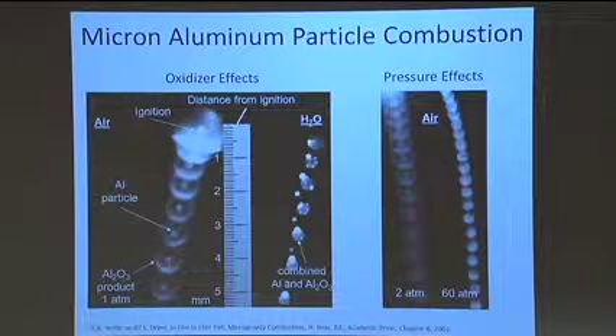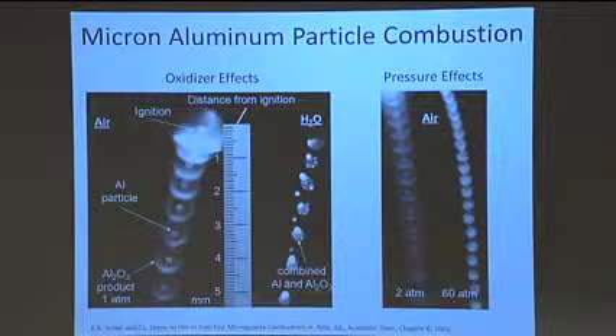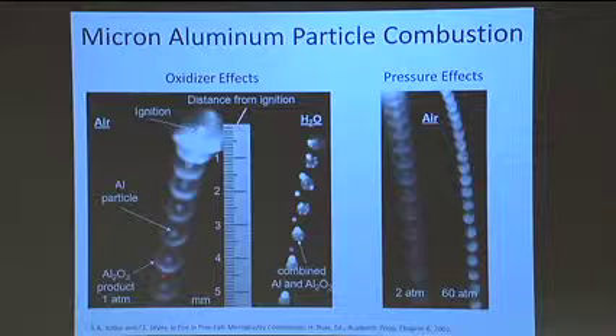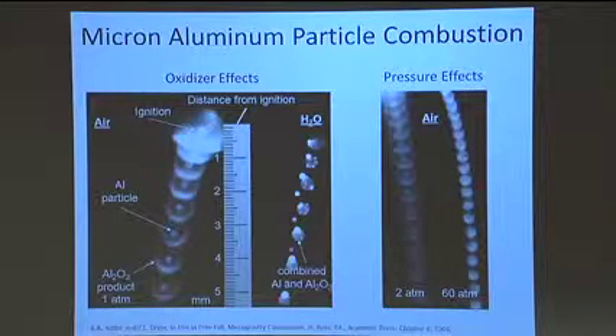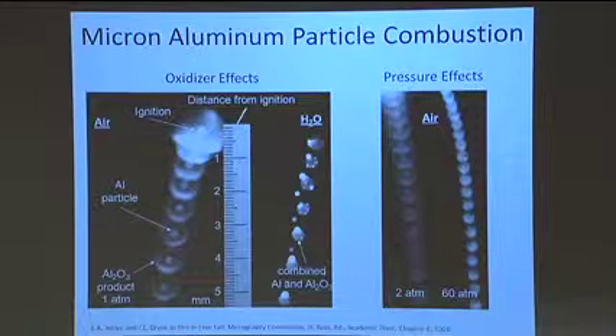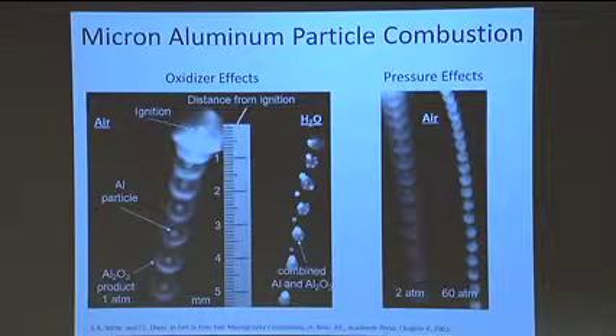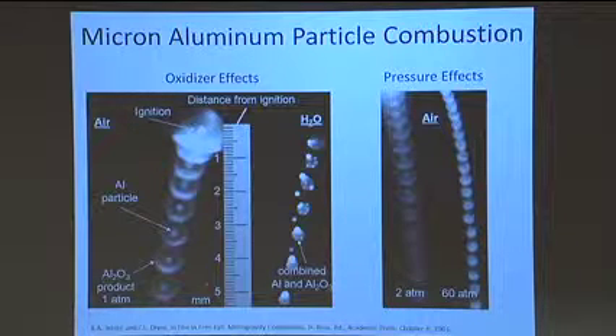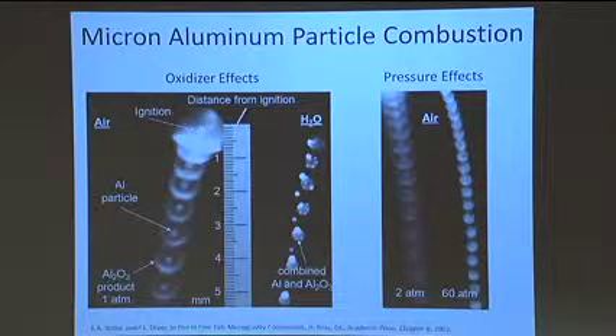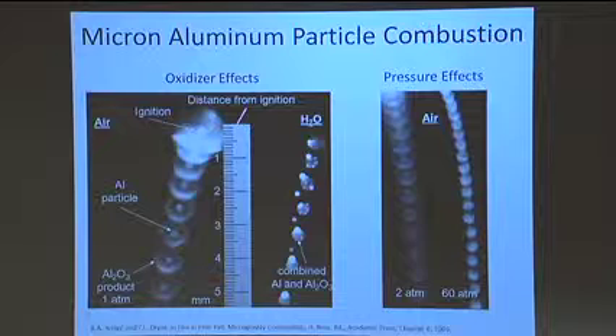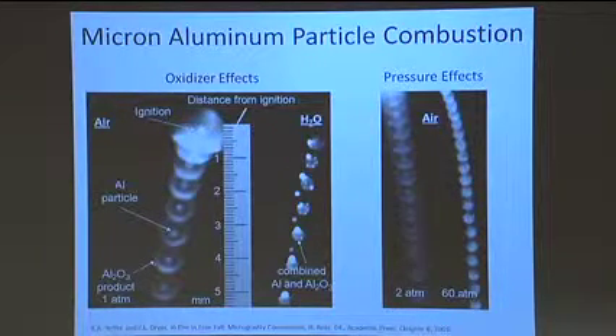And what you can see here then is the aluminum particle is vaporizing. Aluminum is diffusing outward, and this is the spherical reaction zone or flame that sits around the particle that gets to a temperature close to 3,700 Kelvin, 3,600 Kelvin. The heat is fed back to the surface, and I vaporize the aluminum. And the oxidizer out here, which is molecular oxygen and air, diffuses inward. So this scattering you see out here is actually aluminum oxide being formed in the reaction zone.